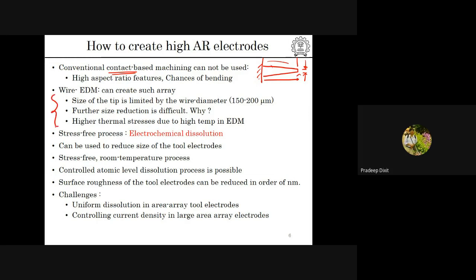We are doing it, but even in wire EDM, if you look at the diameter which is used in the process, either molybdenum wire or brass wire, they are typically 150 to 200 micrometer. Of course, smaller wires are also available, but those are very, very expensive. If you use this kind of wire electrode, because of the higher thermal stress generated during the process, these tips will bend. It should be straight like that, but naturally it is going to be bent like this. So what we have come out with is that it is not possible to create this kind of tool electrode in a single shot.